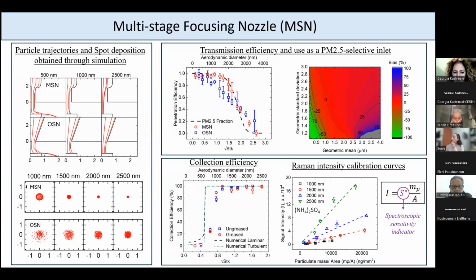Yes. So this is an intrinsic problem that Raman has. Generally, we take any particle size distribution we have, we collect different masses, and we get the calibration curve. Because it depends on the particle size, this should always be accompanied by the particle size distribution that you have every time. Here, because I was able to control the different sizes that I wanted, I was able to get different calibration curves for different sizes. But when you have an aerosol sample outside in the ambient air, you might have some differences from your calibration curve, especially if you have a different peak size. This is something that you cannot avoid, unfortunately.